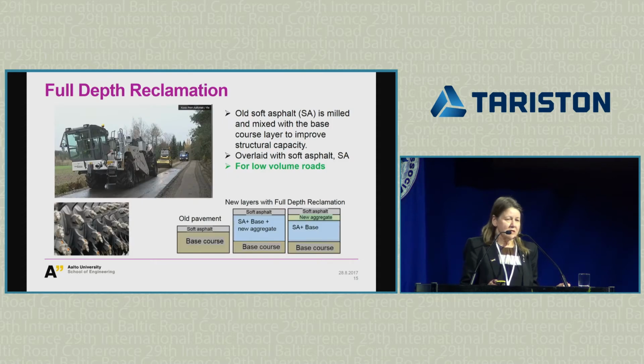So what we do is full depth reclamation, where the old asphalt, soft asphalt, is mixed into the base course and maybe some new crushed material added, and then you just put it back, compact it, and then new soft asphalt. So this is really a structural method to add structural capacity. And it has replaced basically the stabilization in Finland, so this is very popular in low volume roads.